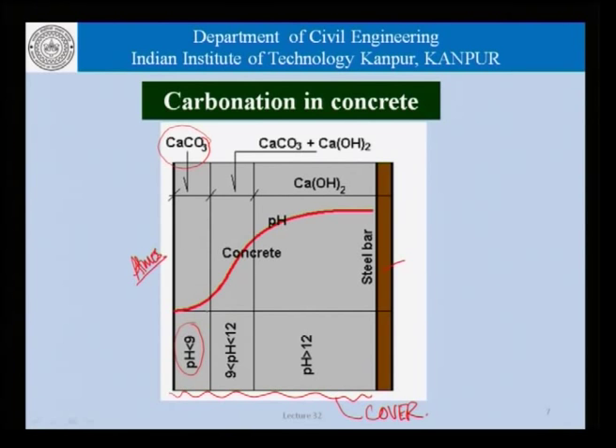So, in this portion here, we can say that we have very little calcium hydroxide left, and we have a reasonably large reduction in the pH. In contrast, we have a region here which is still largely unaffected by the penetration of carbon dioxide from the atmosphere, and we have a lot of calcium hydroxide still sitting here, and the pH is still in excess of, let us say, 12 or 13 or whatever it is.